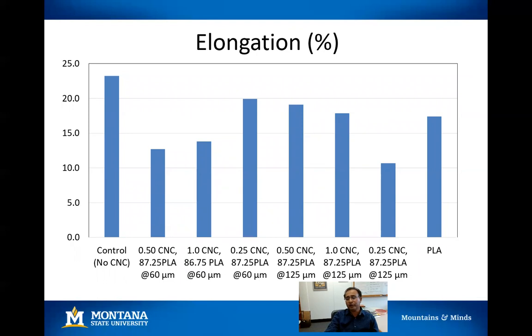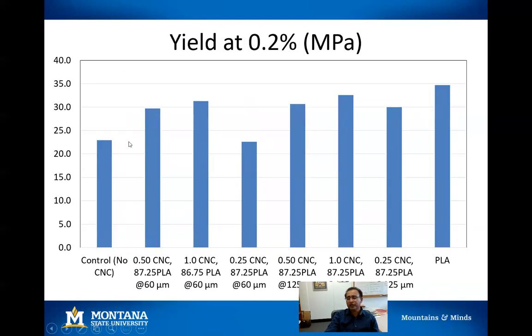Now, elongation is an important property because PLA has a very low strain. We noticed that the composite samples without CNC, but with DDGS and plasticizer, showed the highest elongation, whereas this is the commercial PLA, and all these formulations are somewhere in between. So there were several formulations that showed increased elongation compared to commercial grade PLA. Similarly, for the yield at 0.2%, PLA commercial had the highest yield strength, whereas all other formulations showed a little bit lower value. Some were very comparable to the commercial PLA.